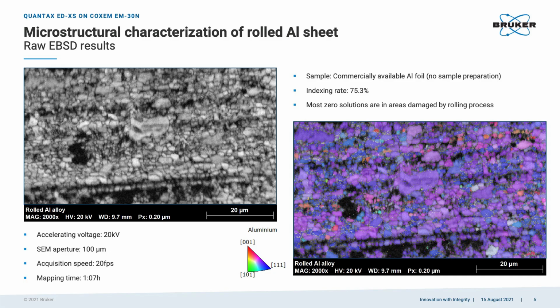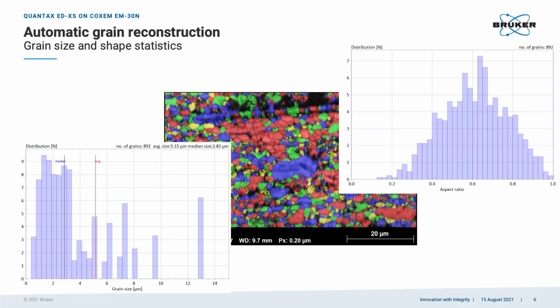The fact that they are mostly blue or purple and not just all the colors means the aluminum foil we can find in the shops has microstructures with grains with a preferred orientation. And if we use this data and ask the software to reconstruct the grains, the process is fully automated and takes a few seconds, we obtain a map that looks like this, where all the grains have been detected and they are colored with a random color so that there are no two neighbors with the same color, simply to make them visible to the human eye.